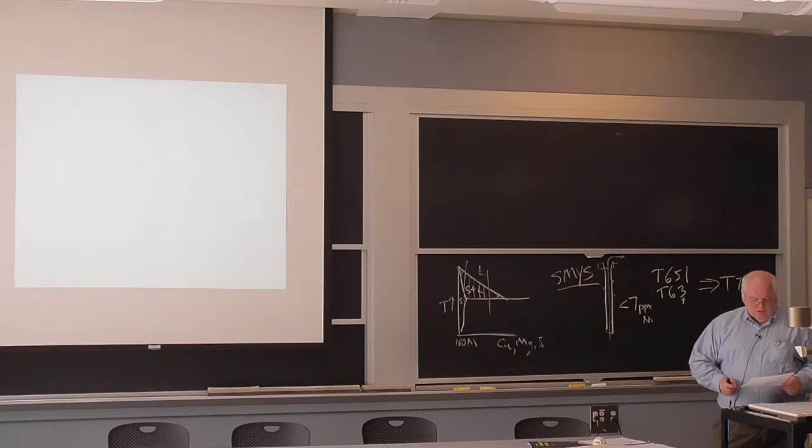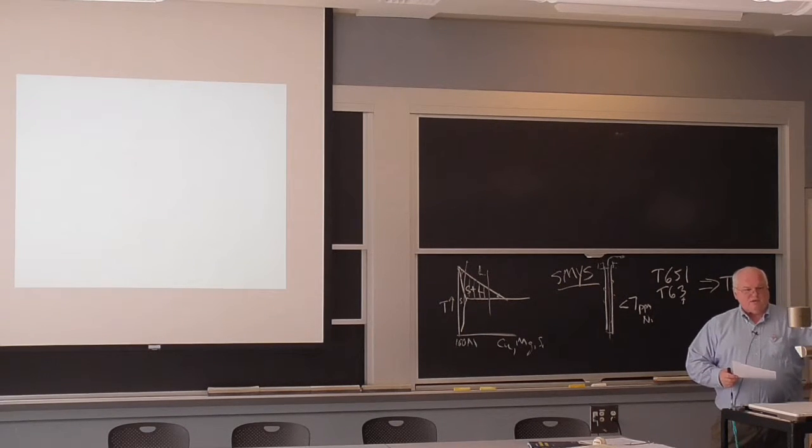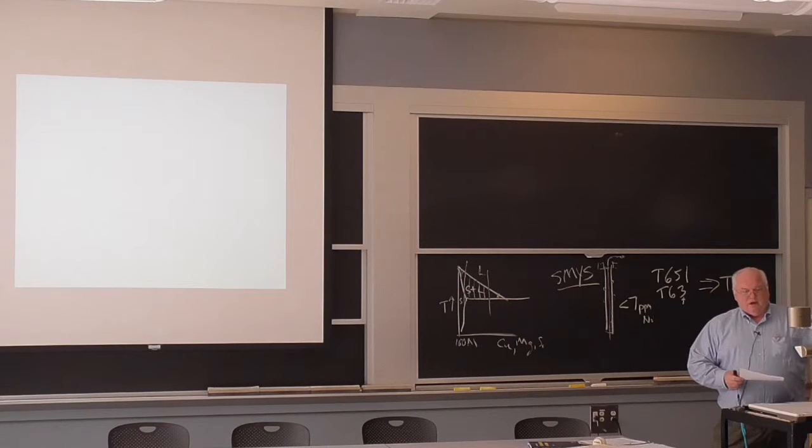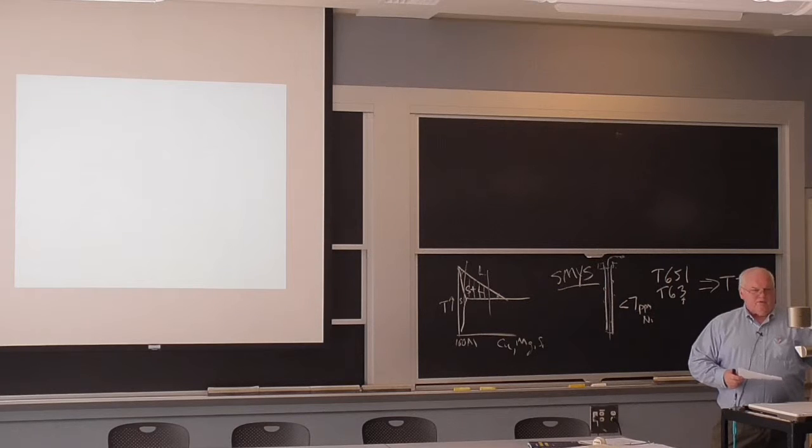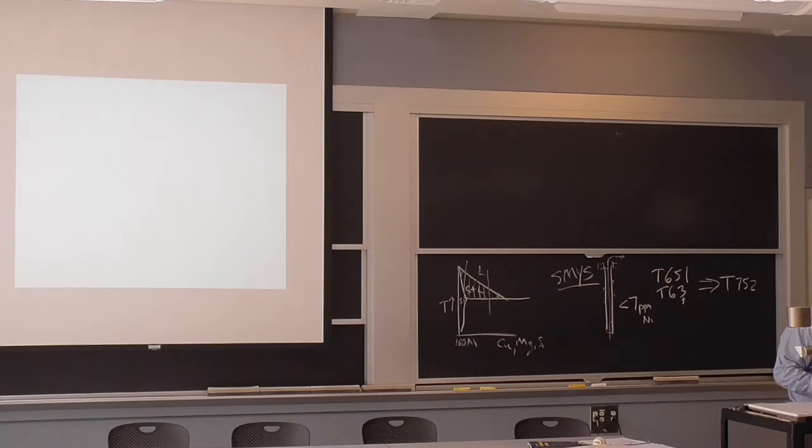Aluminum cracks worse than steel. This is another crack. This is a centerline crack. This is a toe crack going all the way around. You pick the wrong patches. So here's 6061 made with 1100. And here's 2219 welded to 1100 with 1100 filler wire. So if you don't pick the right combinations of filler wire. So it's actually harder when someone comes to me and says, I want to repair something of steel. I say, okay, what's the hardness? What's the chemical composition? From that I can go to Stout and Doty or American Welding Society Welding Handbook, and I can write up a welding procedure with those pieces of information.